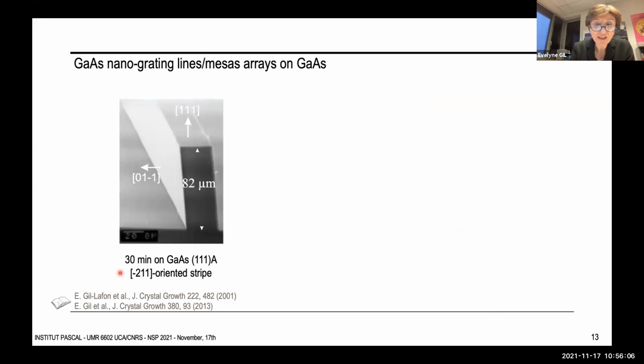So this is the direct illustration of the previous schematic drawing, and it's also a very good exercise of crystallography because this picture shows a cubic gallium arsenide stripe grown on a 111 oriented substrate, and yet not hexagonal because the opening on the substrate was aligned along the -2-1-1 direction. It is exactly what Anna Fontcuberta showed yesterday for this orientation on the nanometer scale.